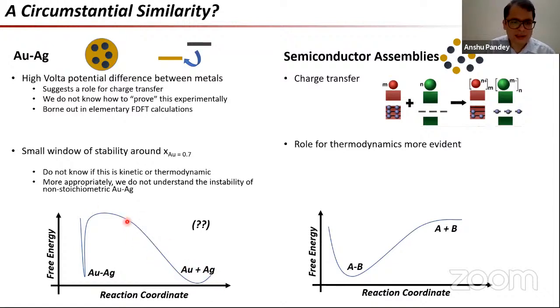But why these are unstable is not very clear, because gold and silver are metals which are soluble in each other in all proportions. So that means that atoms can intermingle freely. And if we talk about engineering on a nanoscale, I can easily make a core shell structure of gold and silver when the core size of silver or gold is larger than 3 nanometers. This instability seems a bit too specific to when we are dealing with smaller sizes like 1 nanometer or so. And why this arises is totally unclear.